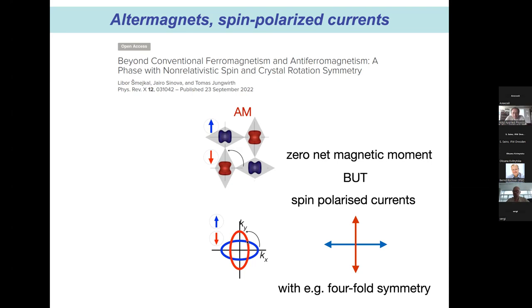If I have spin-orbit coupling, then spin-up and spin-down can hybridize by the spin-orbit coupling parameter. And that is especially important if there's a crossing, of course. And then this crossing, as you suggested already by asking the question, will become an anti-crossing. So you will get a small splitting here, which means that you start with a spin down Fermi surface, it stays spin down, and then it starts rotating as you get close to this crossing point, and then here you continue on the spin up surface. And depending on the size of the spin-orbit coupling, that determines how large the region around this crossing point is where the rotation of the spin takes place.